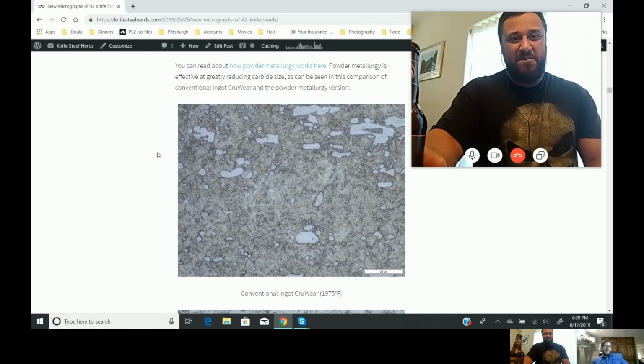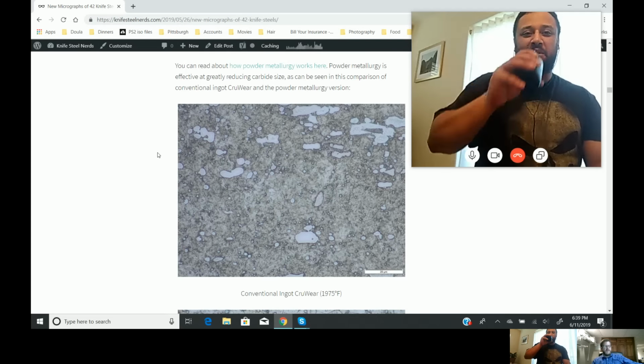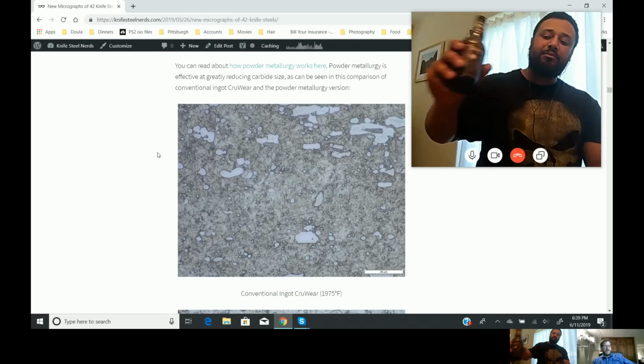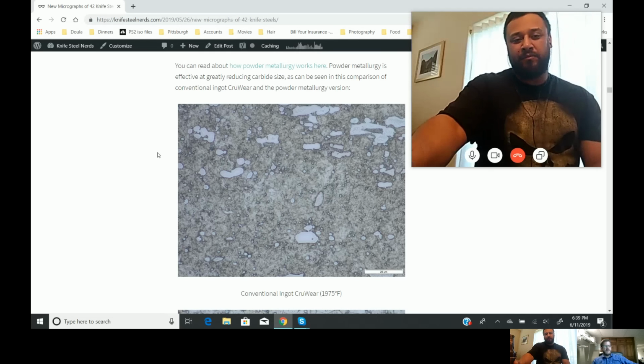So I have a comparison between conventional ingot metallurgy, where you have a bunch of liquid steel and you pour it in a mold and then it cools down over hours. The carbides have much more time to grow in that situation, so they're at high temperature for a long time. We want the steel to have small carbides, but the steel wants its carbides to be as big as possible, because that lowers the energy state of the steel. So they'll grow and grow if they're at really high temperature.